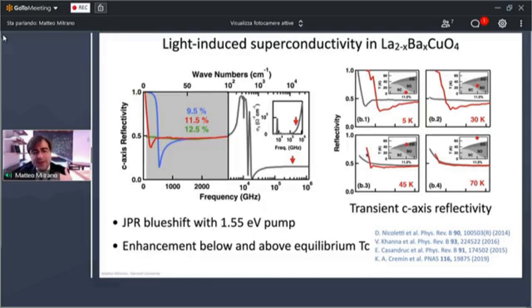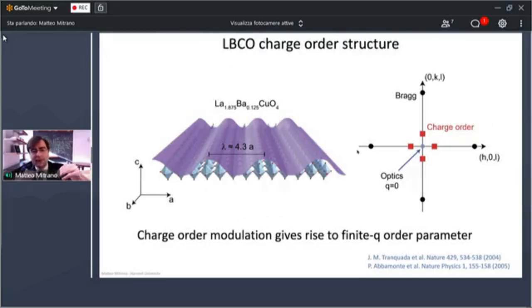parameter. And what we know in this material is that there is actually a competing order that is essentially a density modulation of these carriers. I told you that carriers tend to self-organize in this unidirectional structure, in this unidirectional charge density wave, with a wavelength of approximately 4 unit cells.